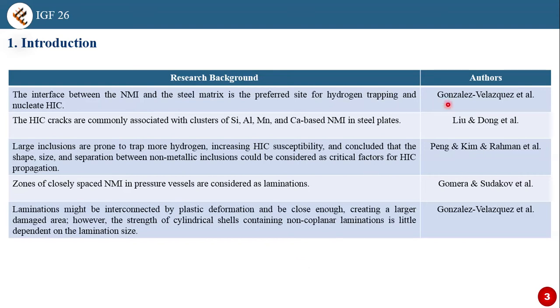In this case, González-Velázquez claimed that the interface between the non-metallic inclusion and the steel matrix is the preferred site for hydrogen trapping. And Liu & Dong also claim that HIC cracks are commonly associated with clusters of silicon, aluminum, manganese, and calcium based non-metallic inclusions in steel plates. Peng, Kim & Rahman indicated that large inclusions are prone to trap more hydrogen, which increases HIC susceptibility, and they concluded that the shape, size, and separation between non-metallic inclusions could be considered a critical factor for HIC propagation.